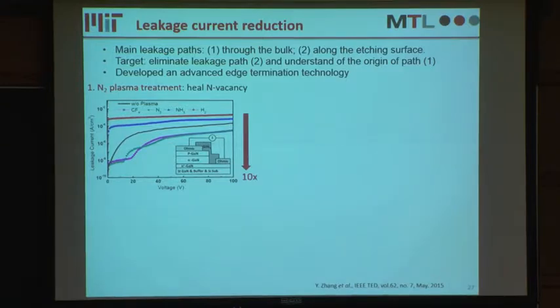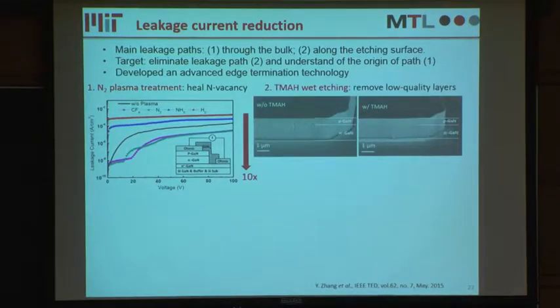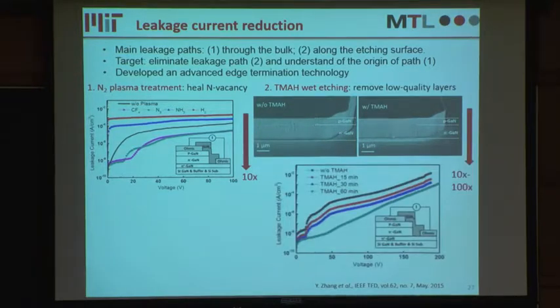The second process is TMAH wet etching. TMAH is a wet chemical which will etch almost all lattice planes of gallium nitride except the C plane. So if we put this structure into the TMAH for some time, say 1 hour, the low quality sidewalls will be etched, but the total etching depth will not increase.